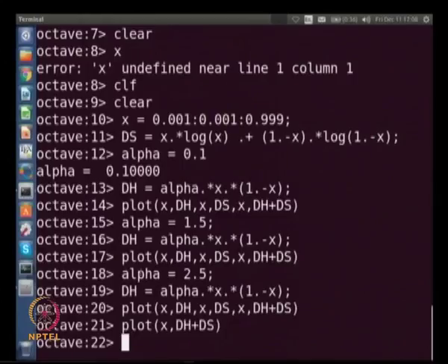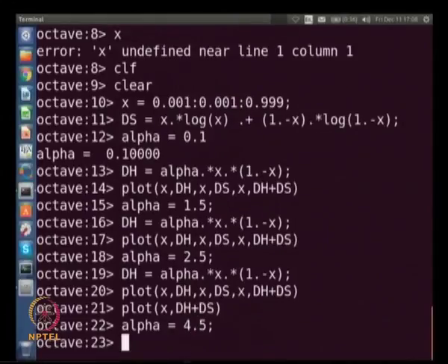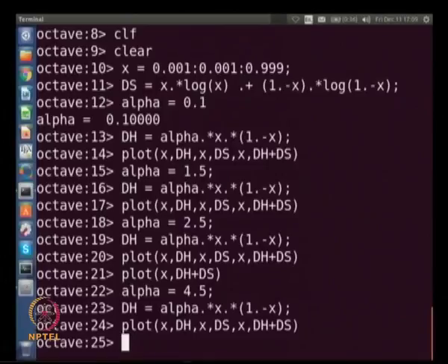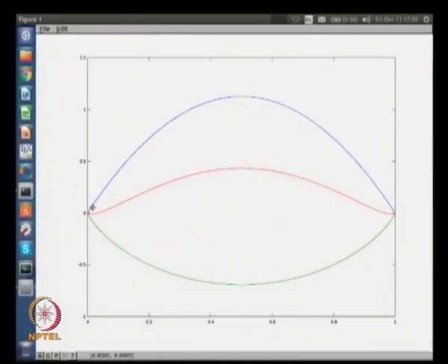There is also another way, of course: we can do that by going to really low temperature. Okay. So, let us go to a non-dimensional inverse temperature, alpha of some 4.5. This is the inverse of temperature. Then what happens? I calculate dH, then I plot the quantity. You will see the unmistakable result: the majority of the portion of this overall free energy curve has a curvature which is similar to delta H. Very small regions at the extremes have curvature like the entropy.